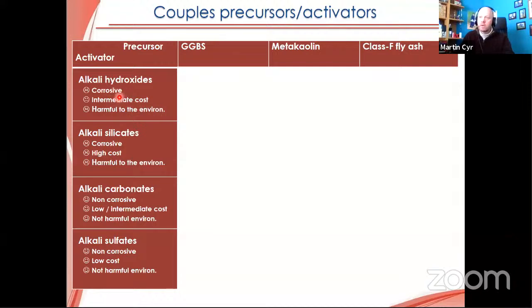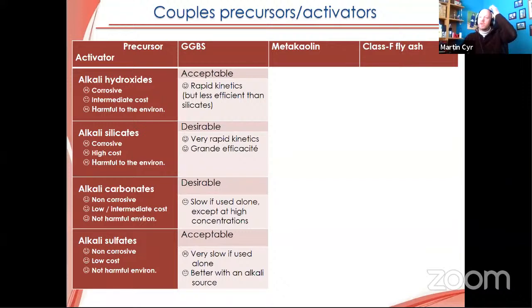The main inconvenience is that some of these activators are corrosive. It's the case for hydroxide and silicates. Carbonates are not corrosive. Also the same for alkali sulfate, but the reaction is quite slow after that. In terms of cost, I will not enter into this, and the same for the environmental impact, it can be a lot of debate. That's not the point here. So if we have a look at the GGBS, for me the easiest one is alkali silicates with very rapid kinetics.